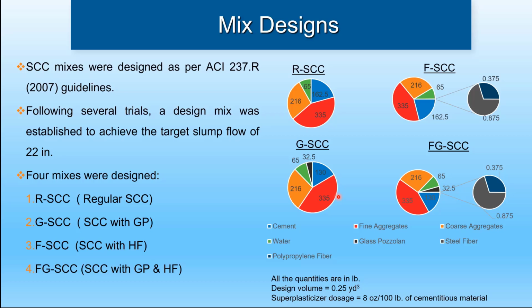The highlights are that the cement replacement rate used for the glass in the SCC was 20%. So 20% of cement was replaced with glass Pozzolan, and the dosage rate for steel fibers was 3.5 lbs per cubic yard, and the dosage rate for polypropylene fibers was 1.5 lb per cubic yard. These dosage rates were kept minimal so as to obtain the right workability of the SCC design mix.